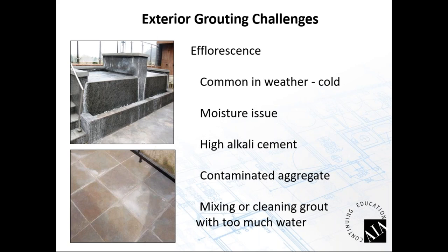Also, a major problem with the grout is that it's a hot day, and instead of covering the work, the installer says, well, the grout's starting to set up, let's use some more water. And they add more water to it, and what ends up happening is they not only wash out the color, but leave more water in it, and then leave an efflorescence problem further on.